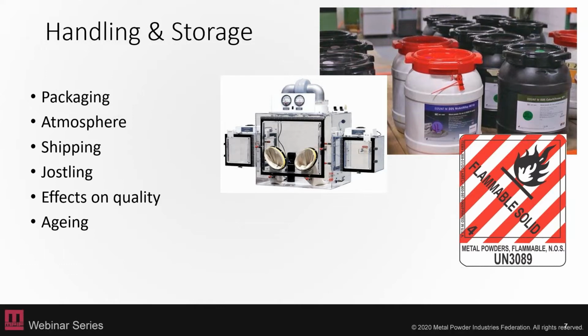When you're shipping those powders, again, there are specific DOT regulations for flammable solids that metal powders fall under, and you need to be careful and make sure your SDS or MSDS is corresponding to those, and that you've included all the proper information for the receiver, and that your container, again, is non-reactive. A lot of the powders that we see are sealed under an argon atmosphere or some other inert atmosphere to make sure that there's no oxygen present in that shipping container that those particles could potentially react with, even if they're fairly non-reactive powders.